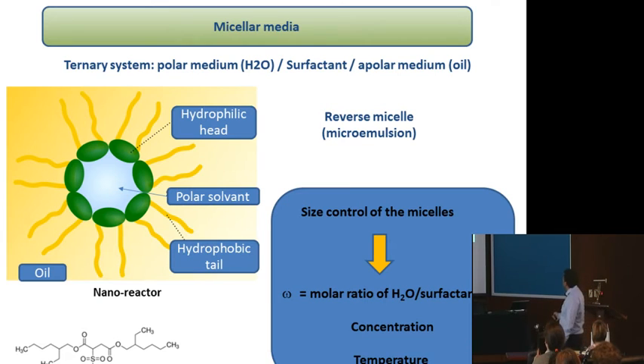So the idea is to control the size of the micelles, playing with the concentrations of the surfactant, the water, and the oil. You often play with this omega parameter, which is a ratio between the water and surfactant quantities. Of course, you can also change the temperature. And changing all these parameters, it's possible to control a little bit the size of the micelles. Of course, this micelle will act as a nanoreactor. So we want to confine the growth of the material inside the cavity of these micelles.